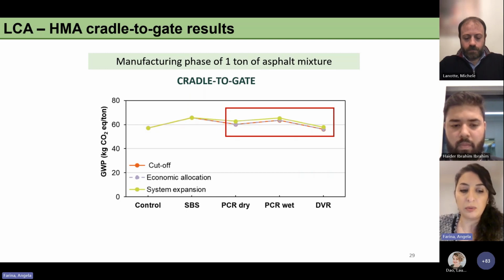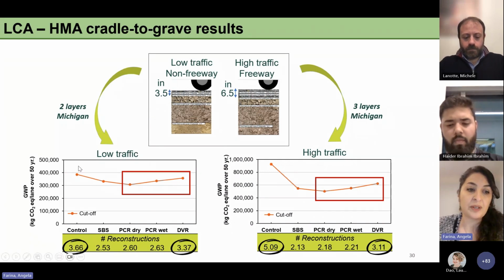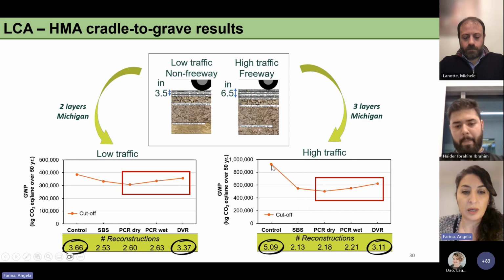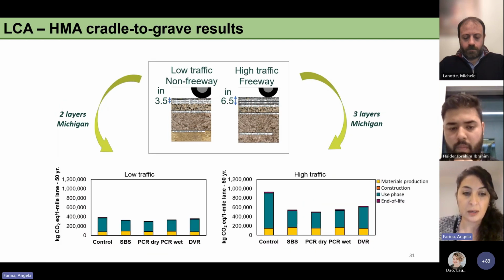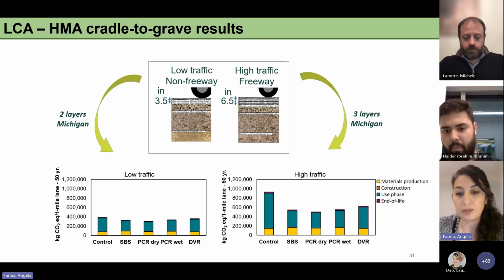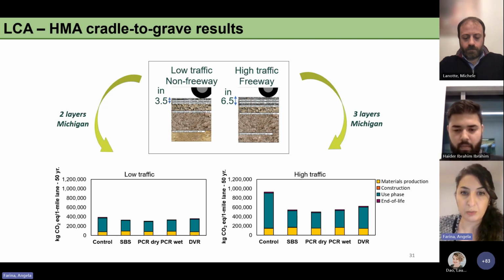However, when we include in the analysis also the performance of each material, these results are the opposite, because now we can see how the control mix is the one with the highest impact compared to the modified asphalt mixtures, both SBS or scrap tires. And this is due to the number of reconstructions calculated based on the performance of the materials. In this graph, we can see how the use phase, so related to the performance, is the phase of life cycle assessment that contributes more to the total carbon footprint of the two pavement structures.